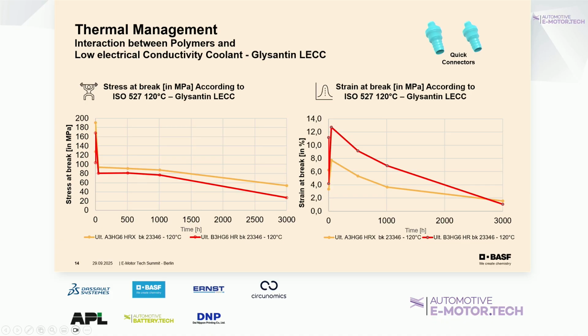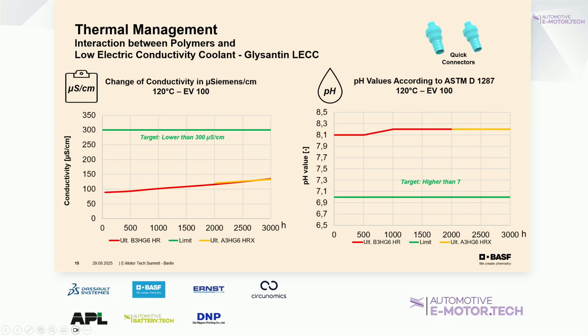So it's not like taking a tensile strength out of the data sheet. If you have this kind of contact with, for example, here the coolant, also the same for the strain at break, you will have an influence on your final part, and you need to consider that during the design of your application. We also tested the change of the conductivity in this case, and there a typical target is to be lower than 300 microsiemens. Also here we are in a good range with our materials. The same is true for the pH values. Higher than 7 is typically a requirement, and also here we've seen no issues with the latest developments.